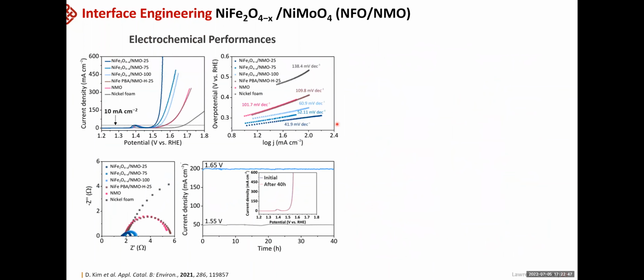So with this, we compare their electrocatalytic OER performance. And as you can see from here, the smallest one shows the best performance compared with the 75 and the 100, which is a larger species, and of course, the bare nickel form or the nickel molybdate. The overall potential was around 260. But the good thing about this catalyst, we found that as we increase the current density, they're still very stable and their overall potential doesn't change much, which shows a good potential for real practical applications.